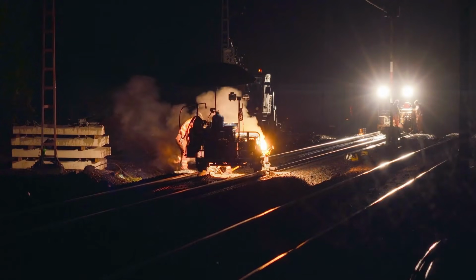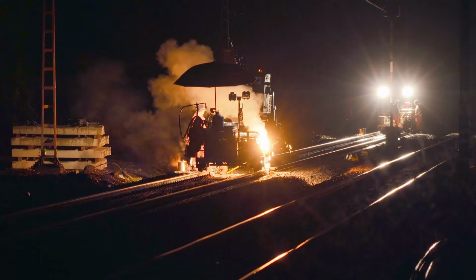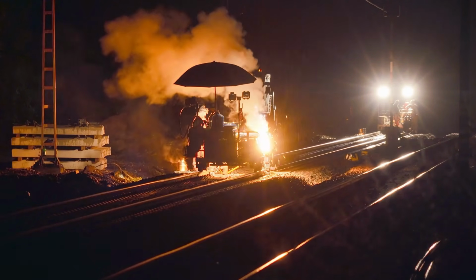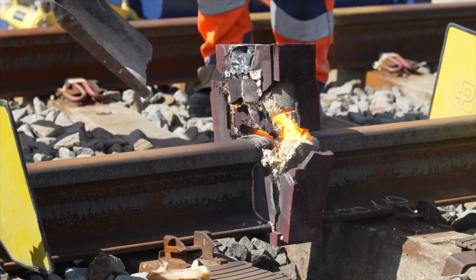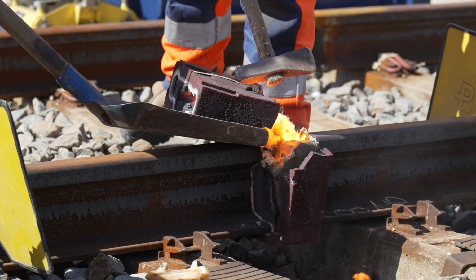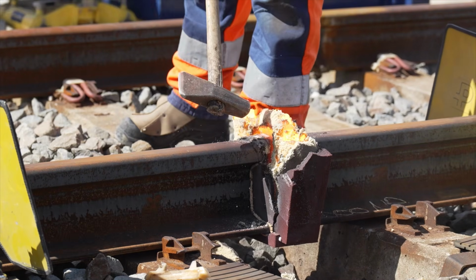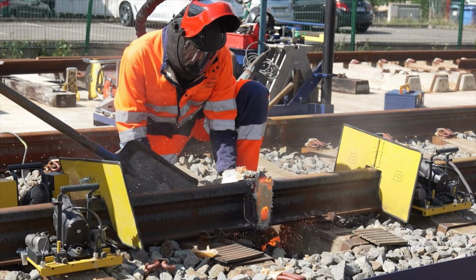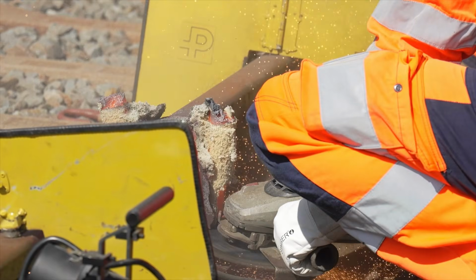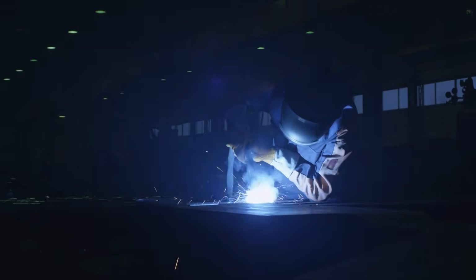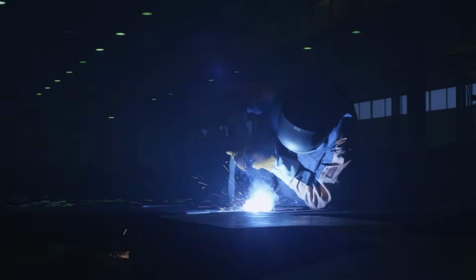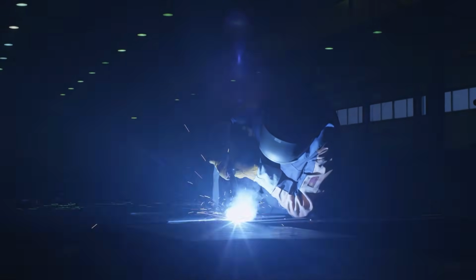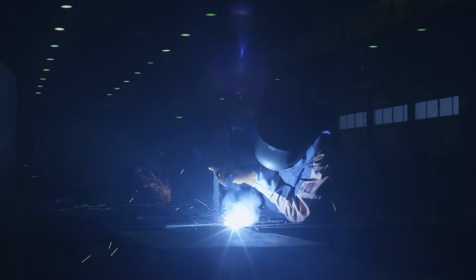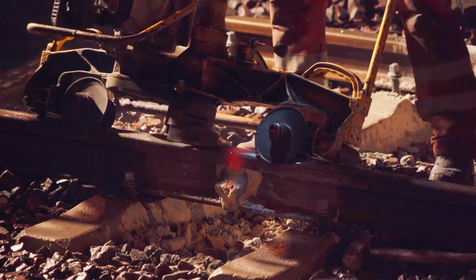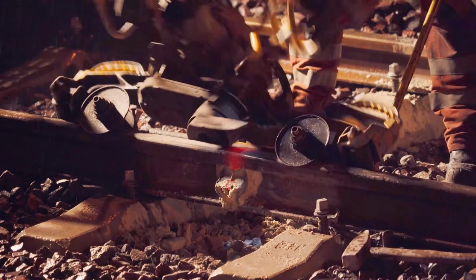The welding process introduces an enormous amount of heat into the rails, and this can cause its own issues. As the rails expand, as metal does when it's heated, any defect or cracks that are already there will expand and worsen. These can be either internal defects or the surface cracks we've already covered. This can lead to those defects weakening the rail. So while the weld itself might look fine, the rail nearby is now weaker and ready to fail. Welding is still by far the best way to join rails. It just needs to be undertaken properly and with care.